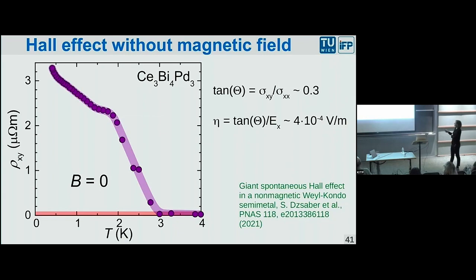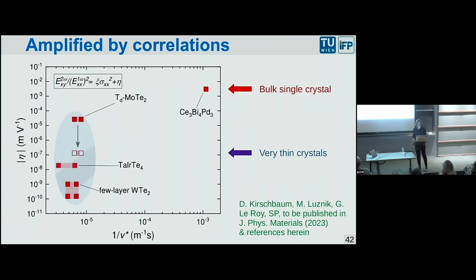We can estimate the size of this effect, and the size of this effect is 0.3 in these units. So this is really the transverse conductivity divided by the longitudinal, or we can also define it divided by the electric field that we need to create the effect, and then it gives some other number. As such, you cannot do anything with it, but I compare it to other systems, and let's do that. In fact, in the meantime, in some non-correlated materials, so materials that are really well described by the single effective single electron theory, this effect has been identified,